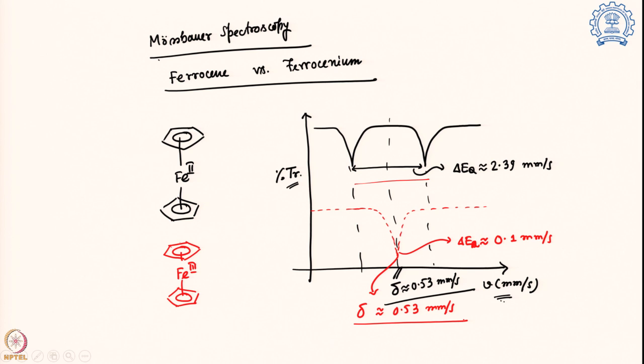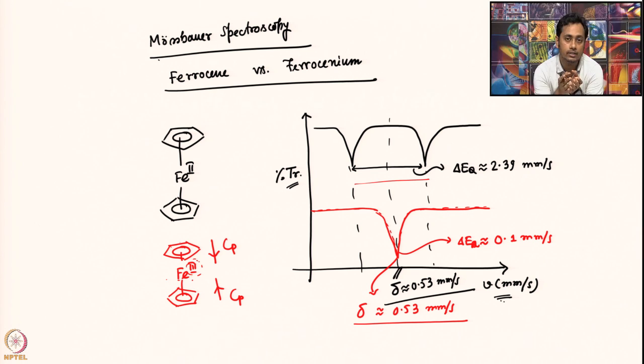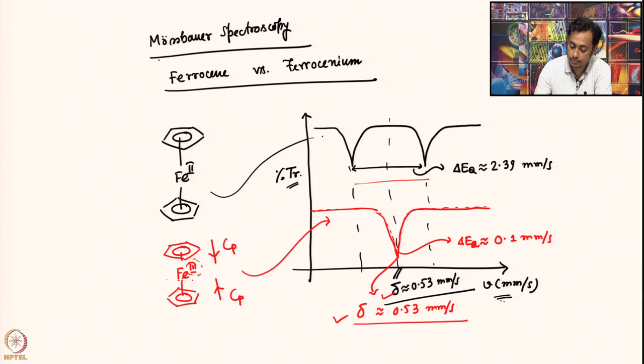And we have discussed why we are seeing this. When you go to ferrocenium, the iron plus 2 becomes iron plus 3. But to stabilize it, more electron density comes from the cyclopentadienyl ring to the iron center. So at the end, the actual electron density present on the iron remains the same whether it is ferrocene or ferrocenium iron, and that is reflected in the isomer shift values. So this is the ferrocenium and this is the ferrocene. And now the only telltale difference between ferrocene and ferrocenium is the quadrupole splitting value, which shrinks down in ferrocenium.